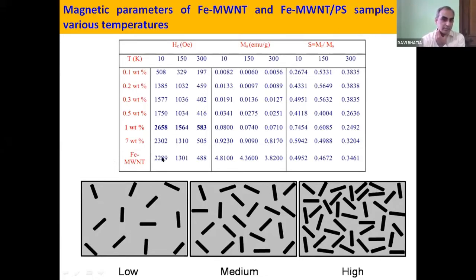We started with Fe MWCNT. We found out that at 300 Kelvin, the coercivity shows 488 Oersted, 1301, and 2289. This is very well understood. The coercivity must increase because the ordering happens at the lower temperatures. Now, if we just go to the vertical points, 7 weight percent shows even higher coercivity. 1 weight percent sample shows the highest coercivity, and the 0.5 weight percent sample and 0.1 are going to lower values of coercivity.